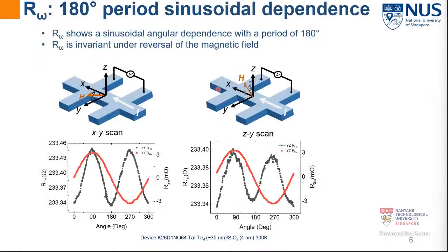Then in this work, we performed the XY and ZY scans for the angular dependent field scan in TaIrTe4. It can be seen that the first harmonic signal, the dark curve, shows a sine angular dependence with a period of 180 degrees, which is invariant under the reversal of the magnetic field, while the second harmonic shows a period of 360.